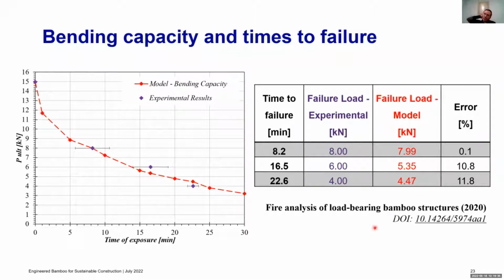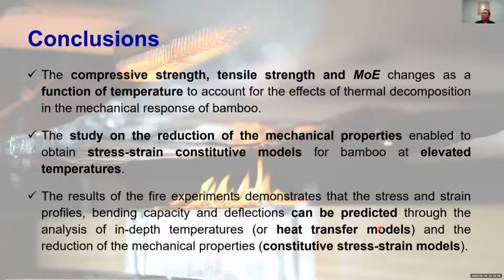So in conclusion, we investigated the reduction of the compressive strength and tensile strength as a function of temperature, and we developed those reduction factor equations and charts that you can use in future bamboo projects exposed to fire. We studied the bending capacity, and we realized that with the stress-strain constitutive models at elevated temperatures, you can calculate the capacity, but you definitely need heat transfer models and stress-strain models.